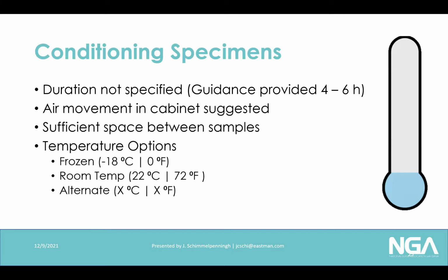The conditioning of the pummel samples is another section that is addressed in this. The duration of how long you condition it is not specified because the thickness of the laminates and the amount of laminates you may have in your conditioning cabinet can change. So there is guidance on reaching the target temperature. You can do that with thermocouples or through experience or through calculation. The temperature options in the standard are frozen at -18°C or 0 degrees F, room temperature, or an alternate as specified by the interlayer manufacturer. The reason there's 3 different ones is because they do respond differently based on the temperatures. Okay.